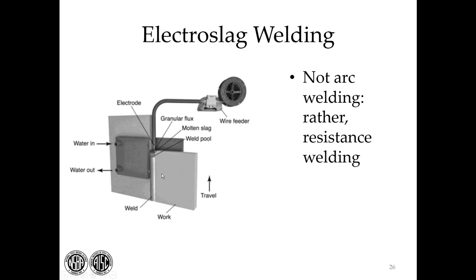You use arc welding to first start the puddle, and then it reverts to resistance welding, and the puddle climbs this column. It'll climb that column at about 2 inches per minute, and it'll be a single pass weld for whatever is joined.